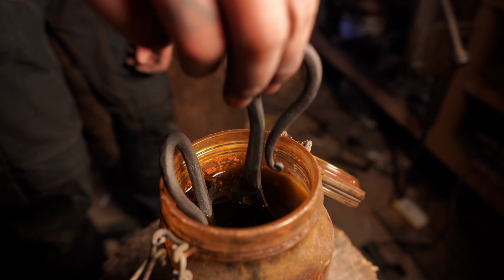Alright, so the blades are now in the ferric chloride, and the idea is that I'm going to leave them in there for about 10 minutes, then take them out, rinse them, give them a quick polish with some fine grit sandpaper, and then I'll simply repeat that process until I'm happy. However, we do have a little bit of a problem. When you're etching, the etchant is eating away a little bit of the steel, creating kind of a texture following the pattern of the pattern welded steel, and that's fine and all, that's actually what you want. However, you can imagine cutting with a pair of scissors that has a bunch of textures and micro grooves in it. It's not going to cut very well.